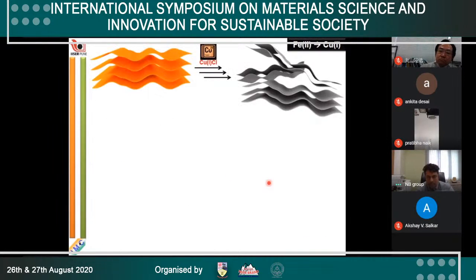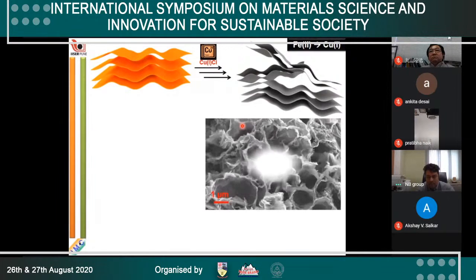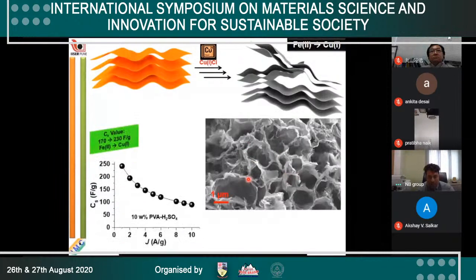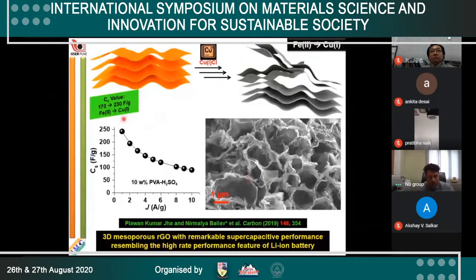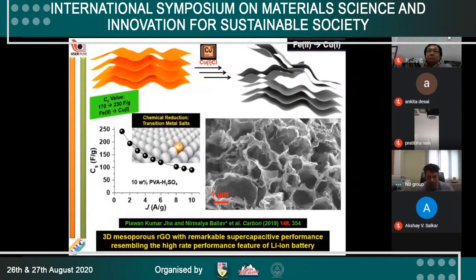Moving on from iron salt to copper salt, copper 1 chloride, we could successfully isolate 3D mesoporous RGO, a three-dimensional structure. And the capacitance value is significantly higher. In the case of iron, it was 170. In the case of copper, it is 230 farad per gram. So, transition metal chemistry is like a golden egg. Now we should not cut the hen.